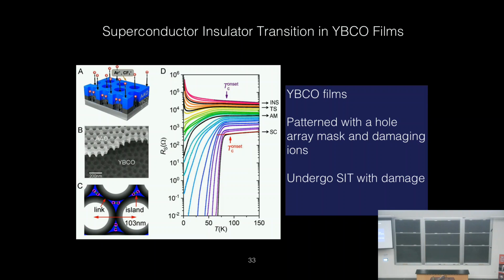Let me show you that here. So this is resistance versus temperature for films of yttrium, barium, copper oxide. As you can see, this one has a transition temperature which is, arguably, depends on where you measure it, above 75 Kelvin. Very high temperature. Those superconductors I was showing you before, the transition temperatures were like 2 Kelvin. There's a little bit of a difference.